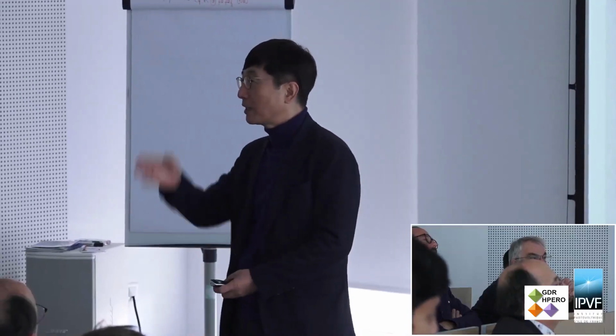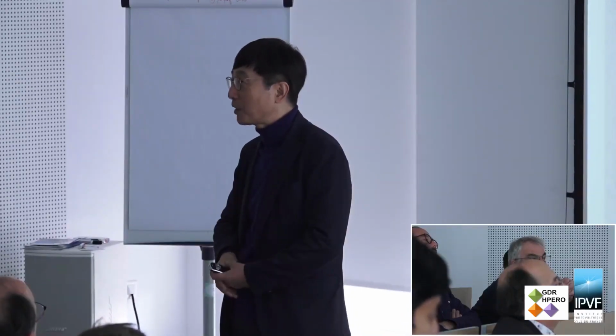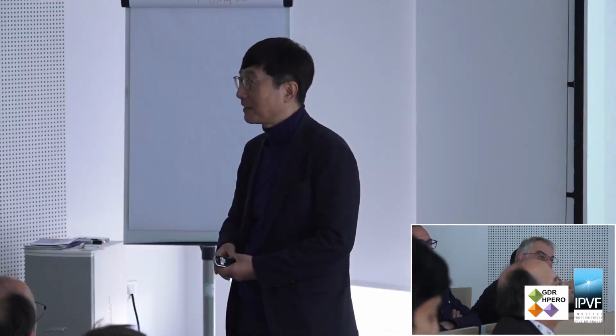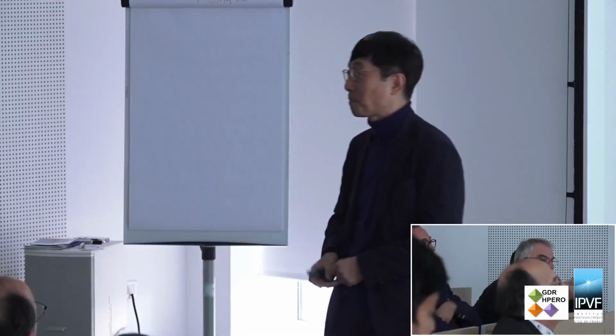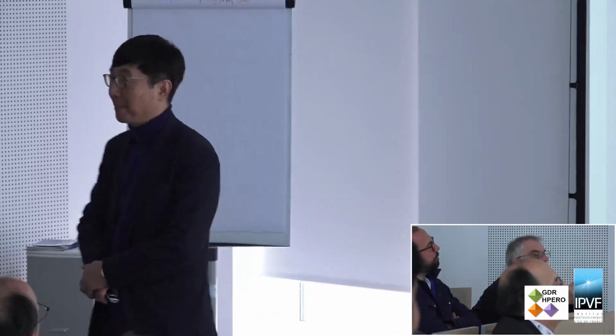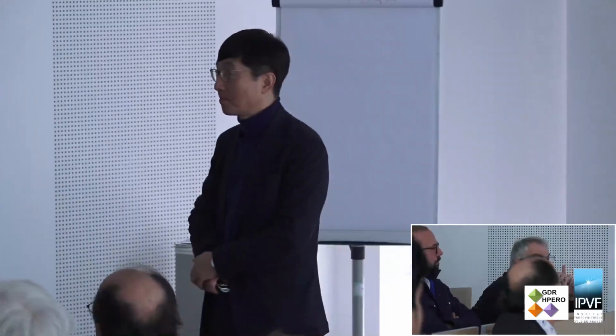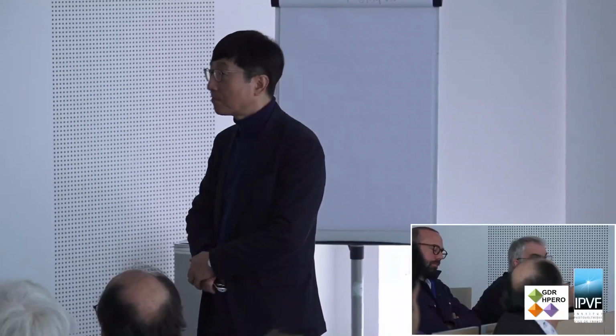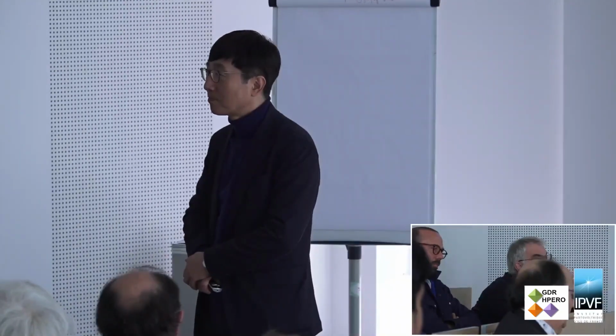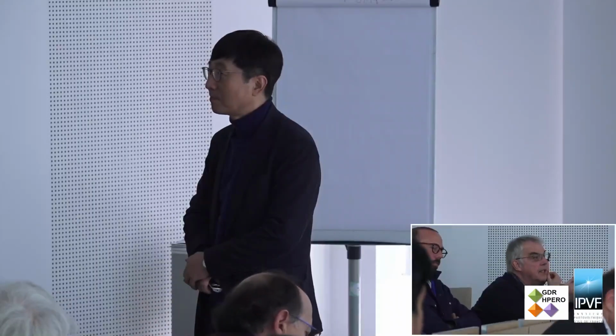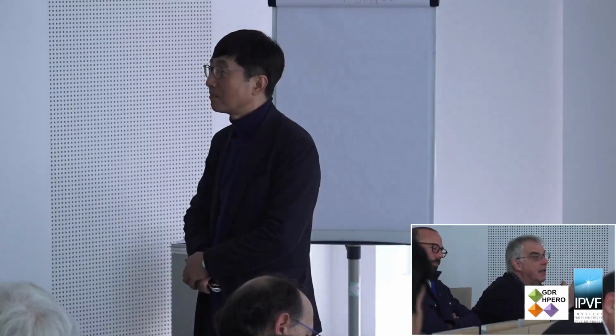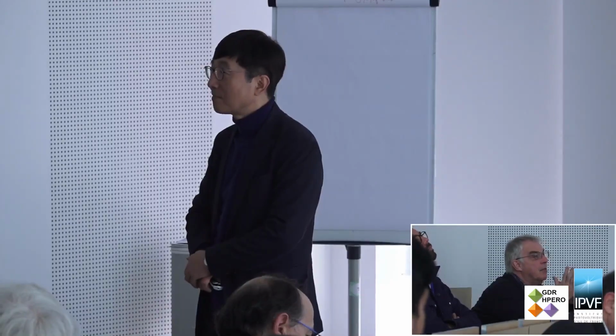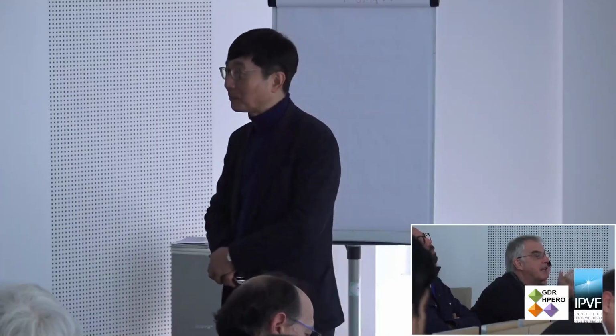Yes. So we are thinking of, we tried, we are preparing the manuscript anyway. And this is a very good idea. And one point is interesting, because you mentioned that the recombination at the interface is very important. What's the main difference between the III-V technologies and all the polycrystalline thin film technologies? In that case they really master very well the epitaxial relationship with the hole transporting layer, because they can manage with all the fantastic III-V methodologies. So epitaxy is very important in that case.